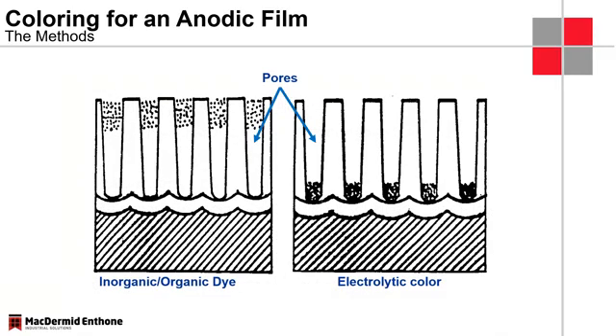And we see that here a little bit better. On the left, this is just our immersion process for organic or inorganic dyes. Because of the size of the dye particles and the very, very small size of the anodized pores, most of the dyes get absorbed in the top part of the pore, and they're really locked in this top part as well. So you can imagine when these parts are subject to any sort of abrasion, this layer will slowly wear away, and we lose some of the color depth as well.